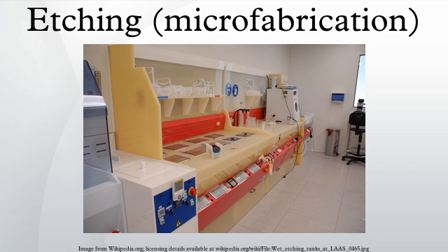Etching a silicon surface through a rectangular hole in a masking material, for example a hole in a layer of silicon nitride, creates a pit with flat-sloping <111>-oriented side walls and a flat <100>-oriented bottom. The <111>-oriented side walls have an angle to the surface of the wafer. If the etching is continued to completion, that is until the flat bottom disappears, the pit becomes a trench with a V-shaped cross-section. If the original rectangle was a perfect square, the pit when etched to completion displays a pyramidal shape.